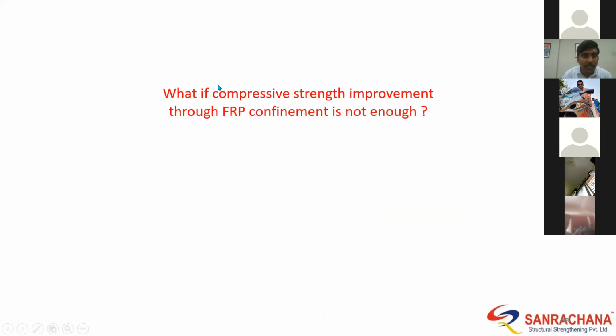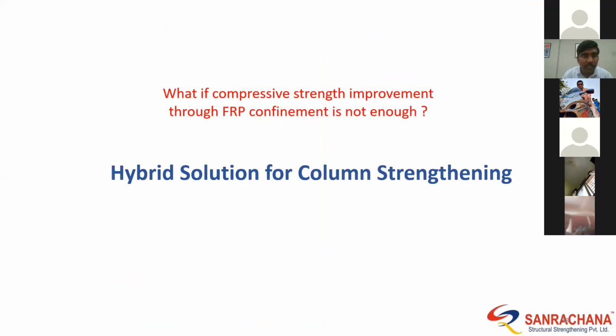So what if the compressive strength improvement through the FRP is not enough, wherein we had only a requirement of an increase of 10 MPa in this particular case, but what if quite a high amount of increase in strength is required? In that case, we go for a hybrid solution, for which I can show you how we typically do it. This is another video.